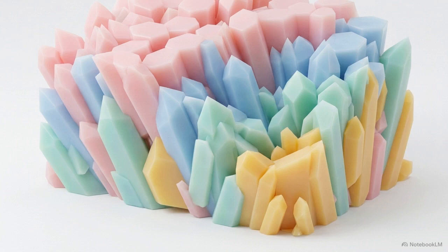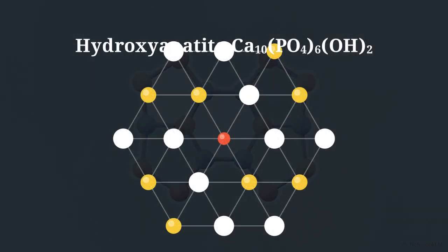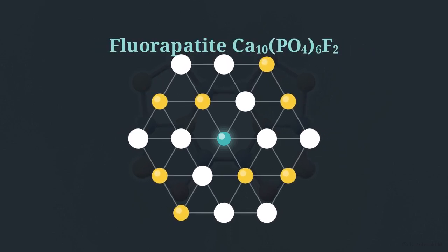Human enamel is primarily constructed from a crystalline mineral called hydroxyapatite. Hydroxyapatite has a specific architectural vulnerability. It begins to dissolve when the local environment reaches a critical pH of 5.5. This 3D vector model shows the hydroxyapatite equation reacting with an incoming fluoride ion. Because of its size and electronegativity, the fluoride ion physically breaks the existing bond and displaces the hydroxyl ion from the lattice. This atomic substitution creates a denser crystalline structure, fluorapatite.